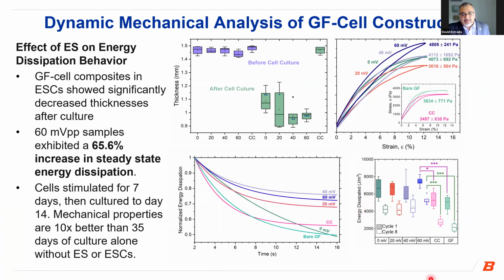But really for cartilage, one of the key things is energy dissipation, right? How well can the cartilage cushion the forces as you walk for your knees, for example, or your hips? And so when we look at the hysteresis under these different curves for the stress strain curves and look at the steady state energy dissipation, here we do see significant results of about 65% increase in the 60 millivolt peak to peak samples for this setup, right?